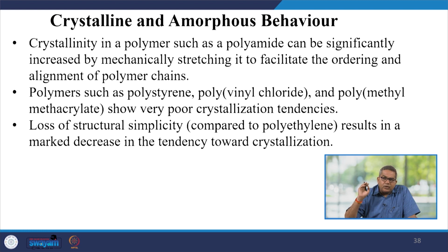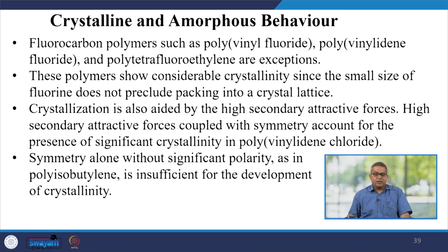Polymers such as polystyrene, PVC, and polymethyl methacrylate, PMMA, show a very poor crystallization tendency. The loss of structural simplicity, compared to polyethylene, results in a marked decrease in the tendency toward crystallization. Fluorocarbon polymers such as PVF, polyvinyl fluoride, polyvinylidene fluoride, or polytetrafluoroethylene are exceptions. These polymers show considerable crystallinity since the small size of fluorine does not preclude packing into the crystalline lattice.